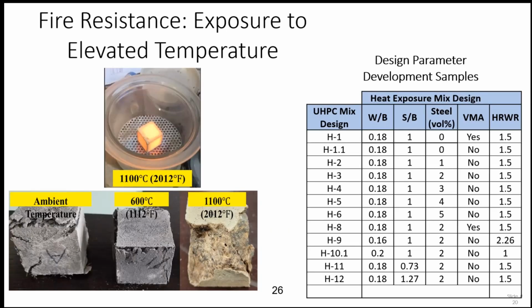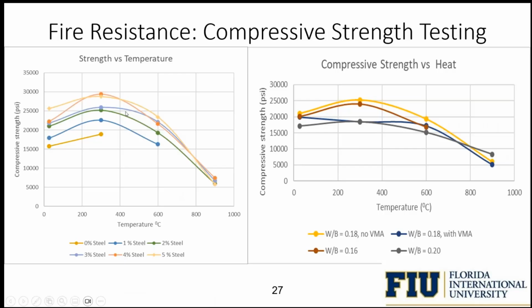I just wanted to show this slide. We are also doing some fire tests because there is some interest in asking, if an accident happens, if a truck catches fire, what will happen? So we are doing some fire tests on this material. I don't have the results to show you, but this is some of the preliminary work that we have seen. We have varied the percentage of the steel. Interestingly, we are seeing that the compressive capacity of the samples, these are cube samples that are cooked in an oven and then subjected to a compressive test, actually increases if you heat it up to about 300 degrees for a couple of hours, then take it out of the oven and do a compressive test.